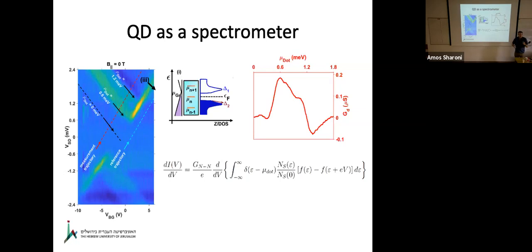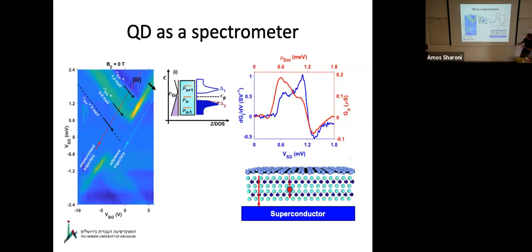Now I can measure this two-band property directly, exploiting the fact that I have direct tunneling from graphene to the superconductor. If I take the second derivative, I see these two peaks here and here, 0.6 and 1.2 millielectron volt. But I also have indirect tunneling through the dot, which gives me the same two peaks at different intensities. That's a bit technical, but it's actually quite important because that shows that the dot couples to the same energy level, but at a different set of probabilities.